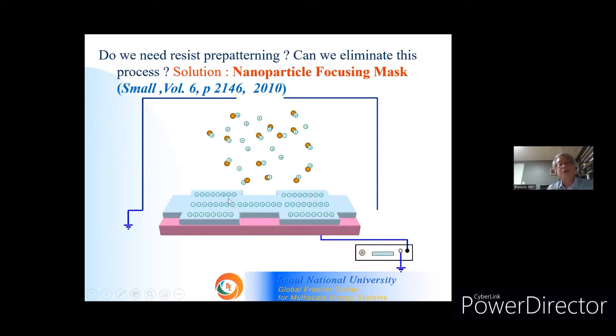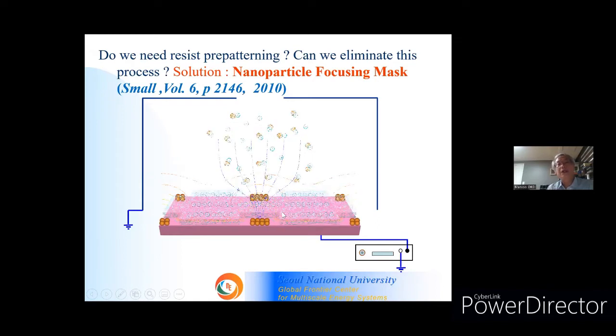As I already told you, ions should be accumulated first before target aerosols are approaching. This accumulation of ions generates this focusing lens, and particles follow this electric field line and deposit only at the center region, and then you remove the mask. Then you generate these nanoparticle patterns.